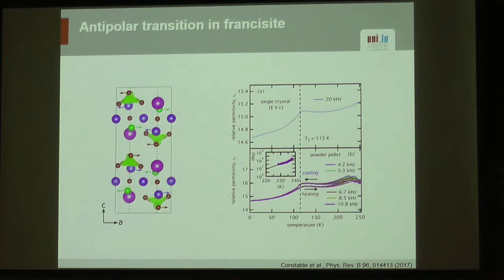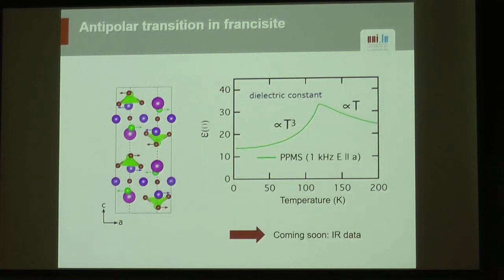If you go for the dielectric anomalies, this is what you will find in the literature, in this paper by Evan Constable some time ago. So they did measure the dielectric constant, and there is some kind of anomaly here. Unfortunately, back then, they were not really aware, so they measured it along the wrong direction. So this has been done again, and this is some unpublished data now that shows you what the dielectric anomaly is like, so it's really significant.